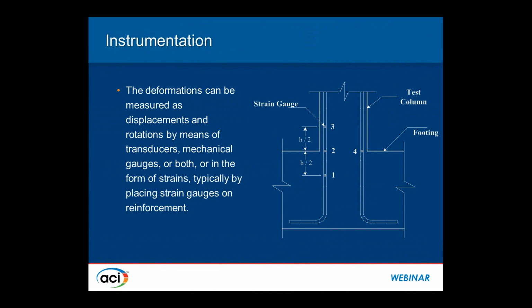And strain gauges have to be used carefully. They are very valuable gauges. They are easy to use, easy to place, especially on reinforcing steel, but one has to be aware of the fact that they pick up localized strains, and we should not place over-reliance on these strain gauge readings. As valuable as these gauges may be, they can at times be deceiving. But it's always good practice to provide strain gauges, obviously one at the critical section and then at least one or two above and below to monitor yield penetration into the adjoining member or within the member itself.